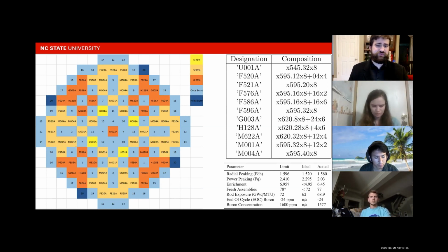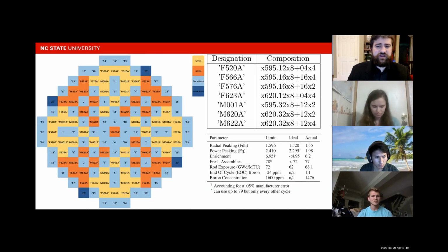We were able to reduce the enrichment levels between the two cycles, after which we were given an additional constraint that there be only 2 different enrichments. This was the final loading pattern that we created. It satisfied all requirements and had only 6.2 and 5.95 as enrichments. And this is the one that we used for financial comparison against the previous group's loading pattern, for which I'll pass it off to Amelia.